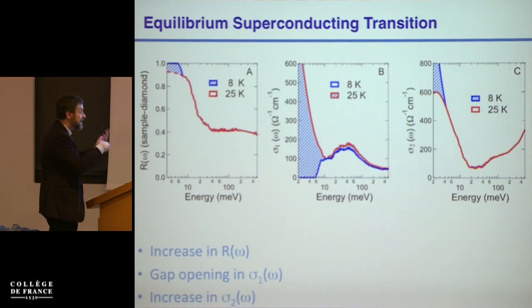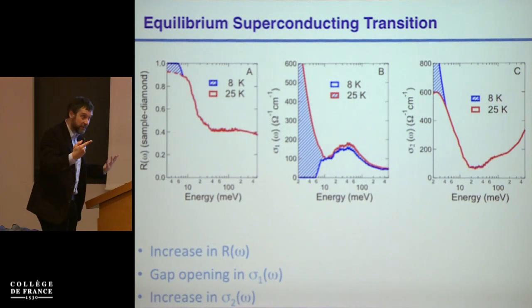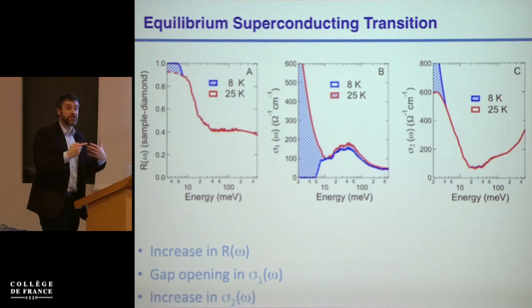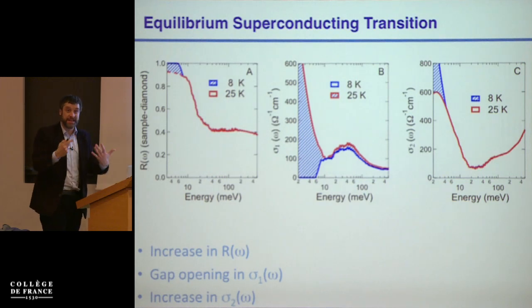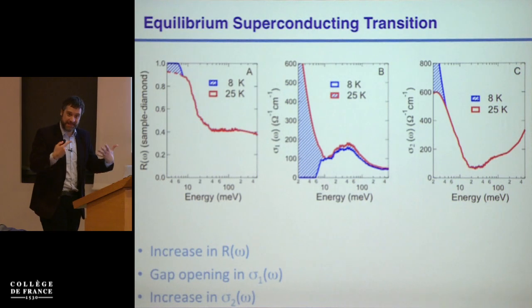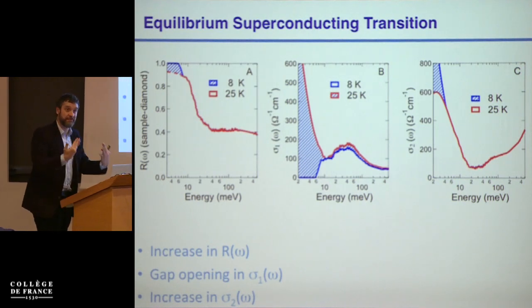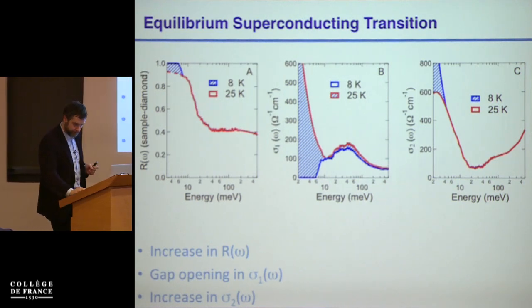So these are features in the AC spectrum, especially the divergent sigma 2, that are considered to be indicative of the superconducting state. Okay? And much clearer in a general sense than the plasma edge, although they're probably similar, at least at the intuitive level, they're easier to digest.